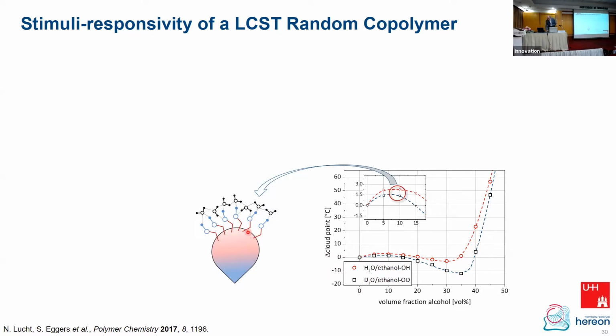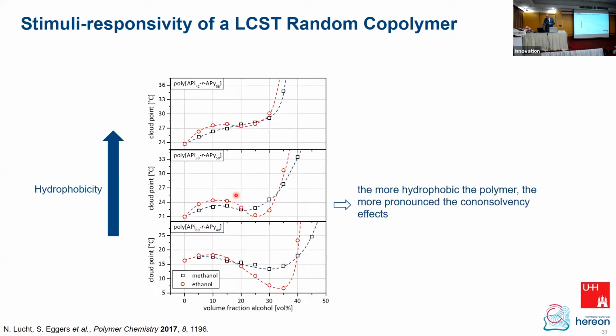So this slight hydrophobicity of the polymer can nicely interact with ethanol or methanol, and then you have again also a hydrophilic, let's say, situation on the former hydrophobic part of the polymer. Okay, and now depending on the composition of the copolymer, you have more or less pronounced these effects.